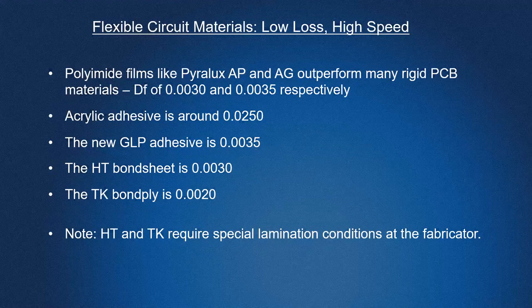Looking at the low loss and high speed part of this, as you can see from here, these are the DF factors, or loss tangent dissipation factors, for the different materials. You see the acrylic is lossy. Doesn't mean you can't use it at, for example, 2.5 gig. Just be aware that your loss is going to be higher than if you use some of the other materials. It really depends a lot on the design. The standard materials like AP and AG outperform many of the rigid PCB materials. If people are familiar with things like Rogers and Megtron 6 and ITERA MT40, those are very low loss materials used in high speed rigid PCBs. AP is already there. It's already in the same loss group as those materials and has been for a long, long time.